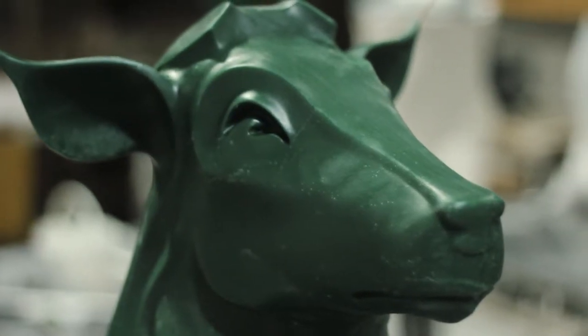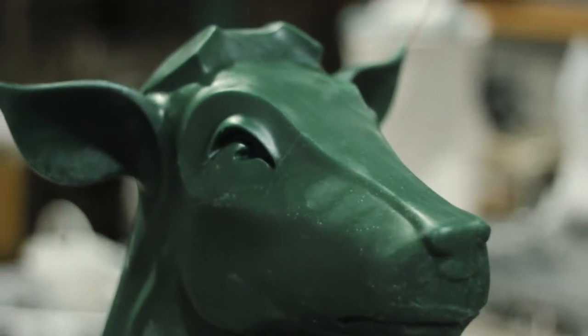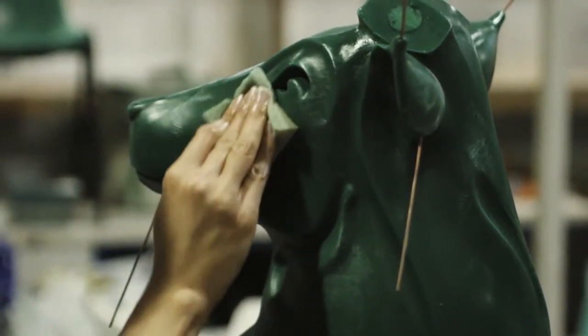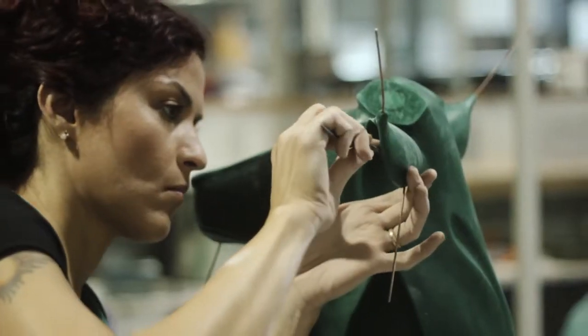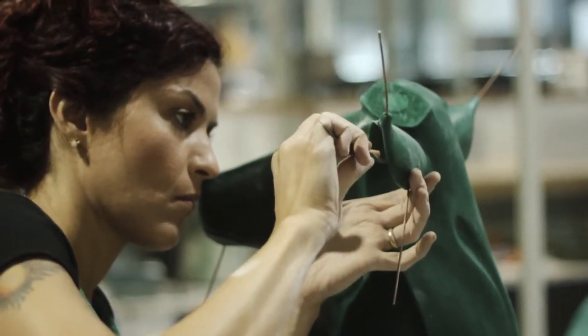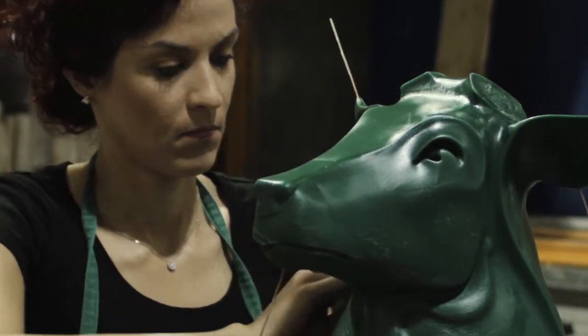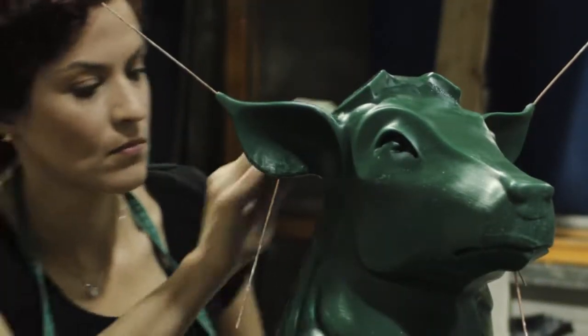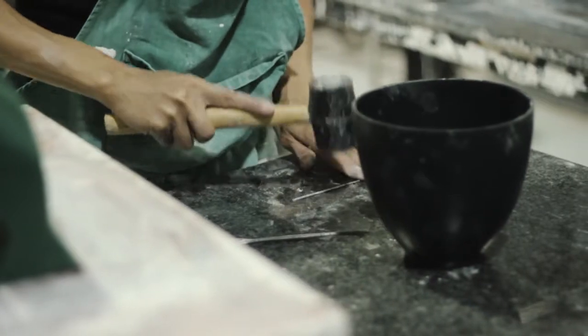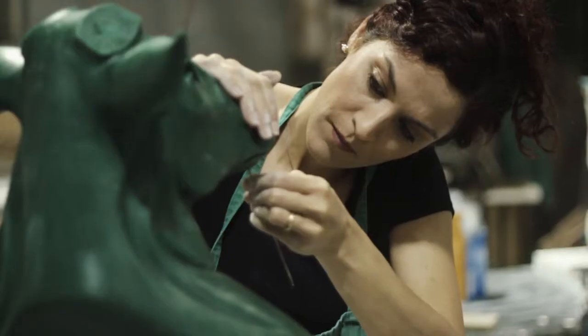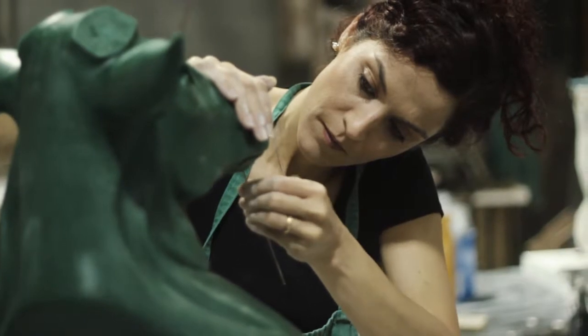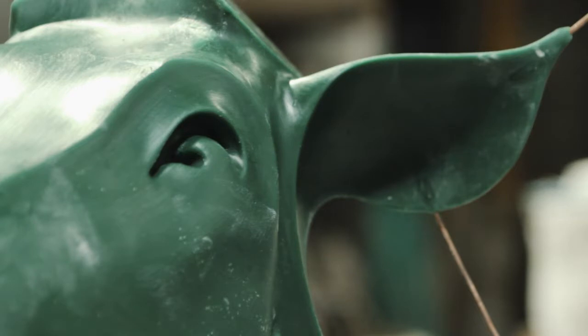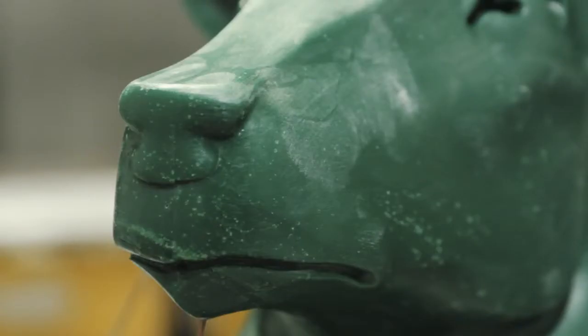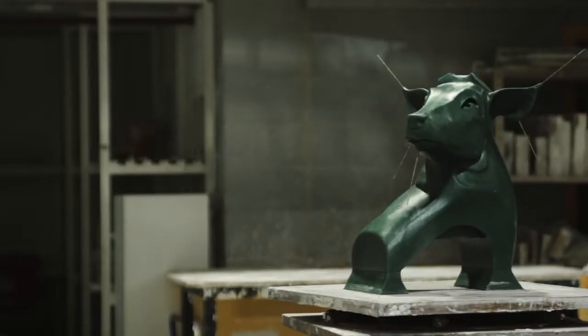Once the wax is out of the mold, I clean the seam line and I make sure the surface is nice and smooth. And then I normally take copper wire or any type of metal wire, and I stick it into the high parts of the model, so wherever there might be air trapped, there will be a hole to allow air to flow. In the stag itself, I have probably about five copper wires that I put mostly in the ears and in the antlers.